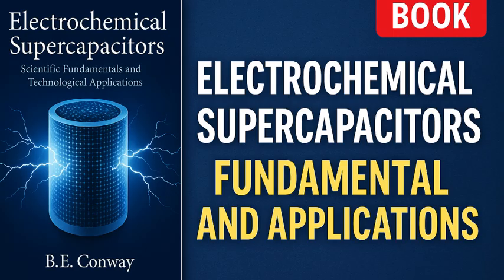In practice, making a carbon electrode for a supercapacitor involves mixing the carbon powder with a binder like PTFE or PVDF, which hold the particles together, and sometimes a conductive agent like carbon black. If the carbon is not graphitic enough, one might add a bit of carbon black to ensure good conductivity. This mix is coated onto a metal foil current collector or just fabricated as freestanding electrodes. Typical electrodes might be 100 to 200 micrometers thick layers of packed activated carbon and binder. Two such electrodes sandwich a separator soaked in electrolyte to form a cell. This simple, robust construction is one reason supercapacitors can last so long. There is no delicate crystal lattice or phase transition, just a porous carbon scaffold holding charges.